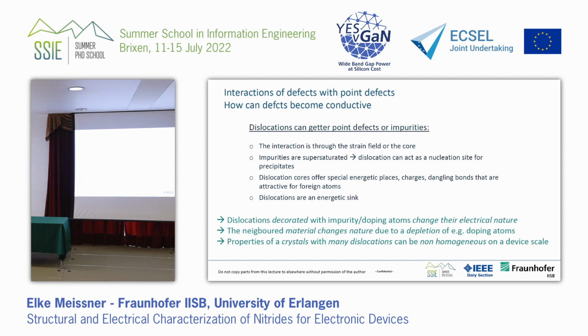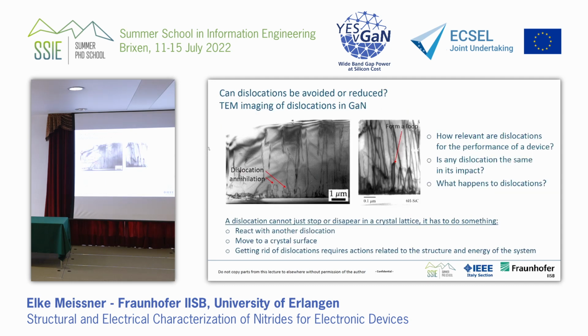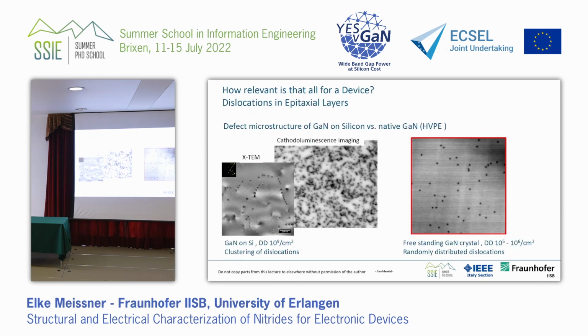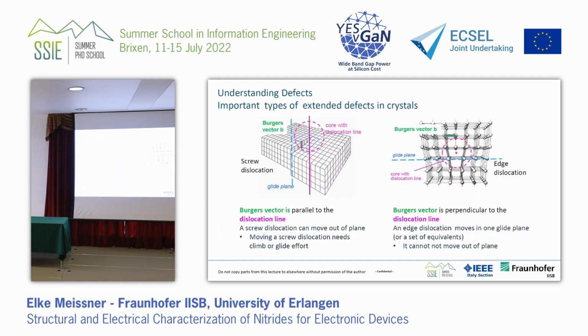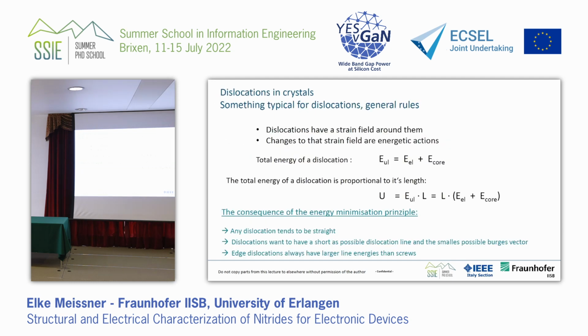And then imagine if you have dislocations that are unevenly distributed, like we have seen before. You have many, and imagine this big cluster collects more dopants. And then you don't have dopants here anymore. But if you have more distance, this is less severe. And you can see that this is true if you measure it.